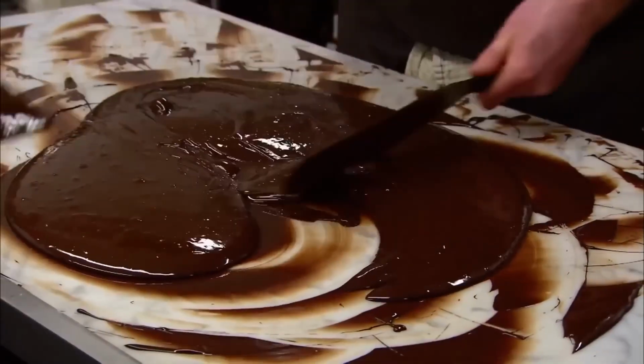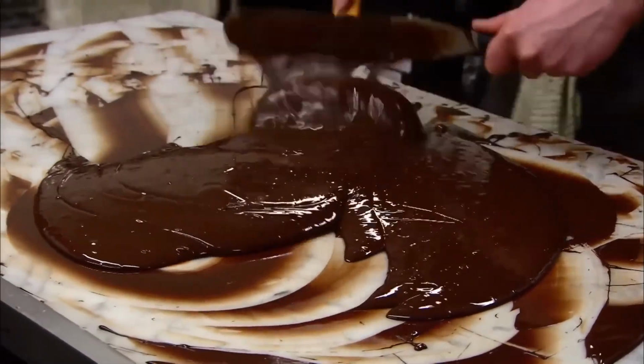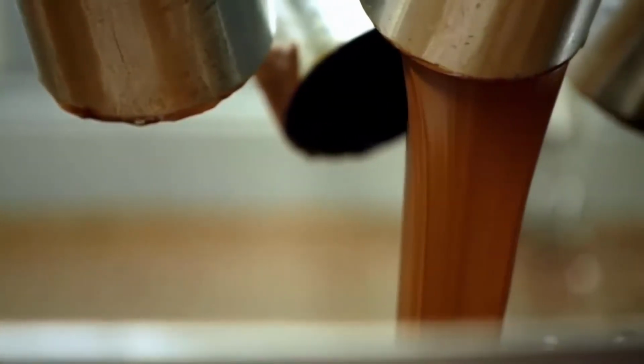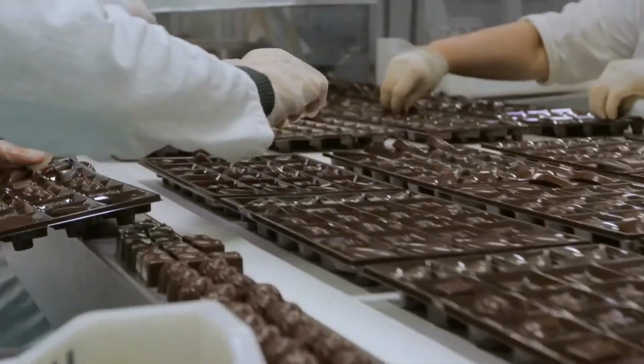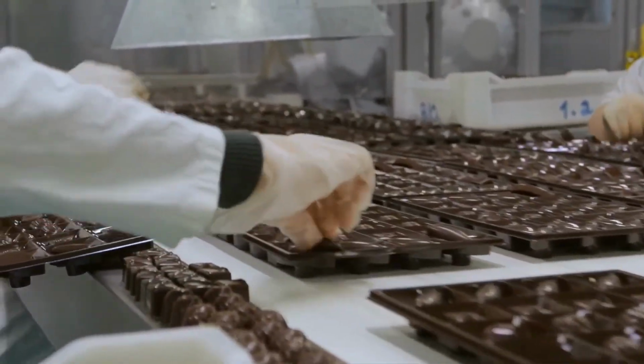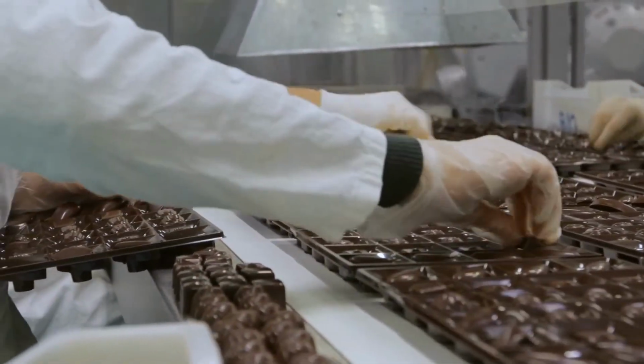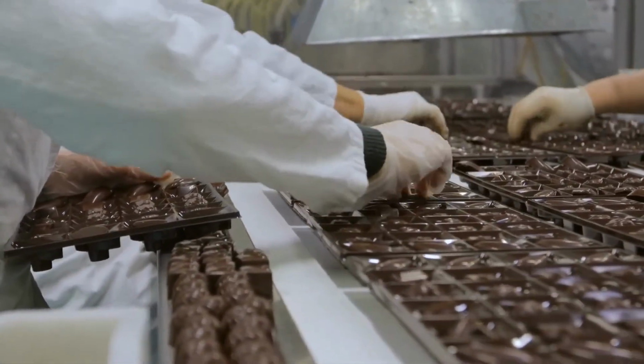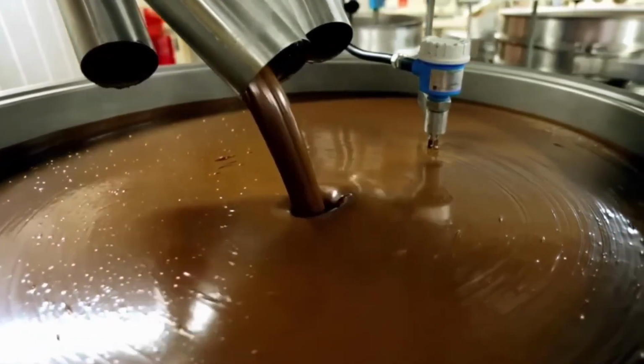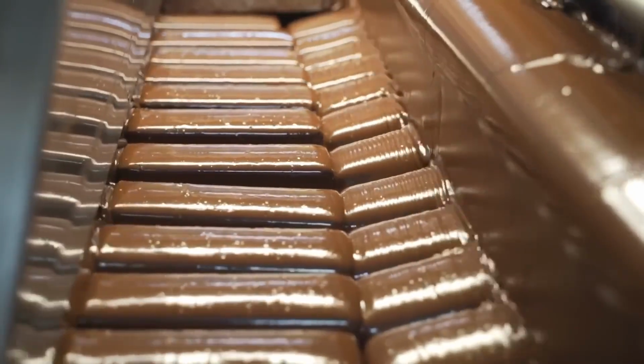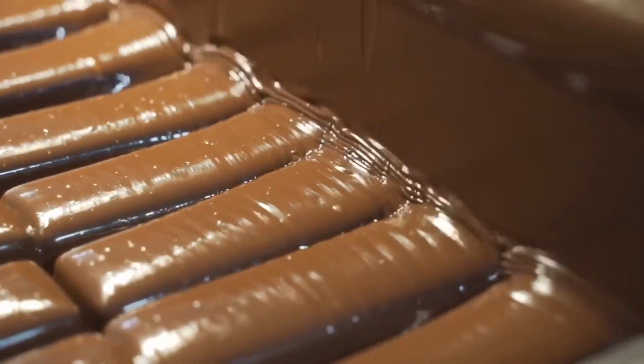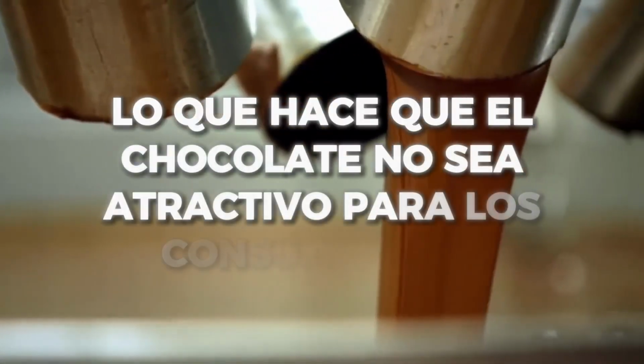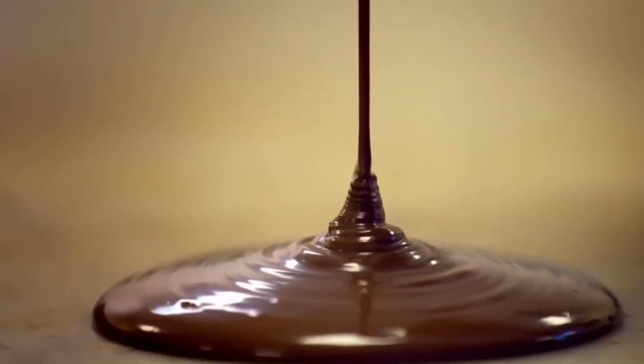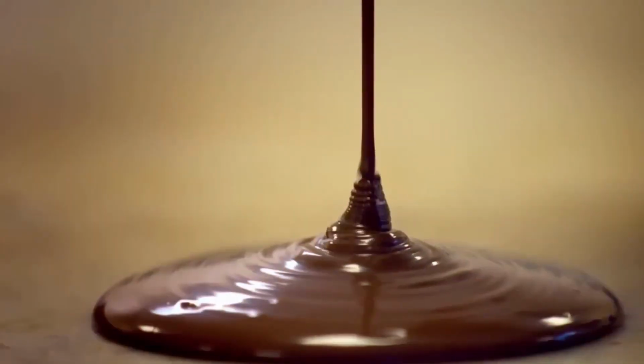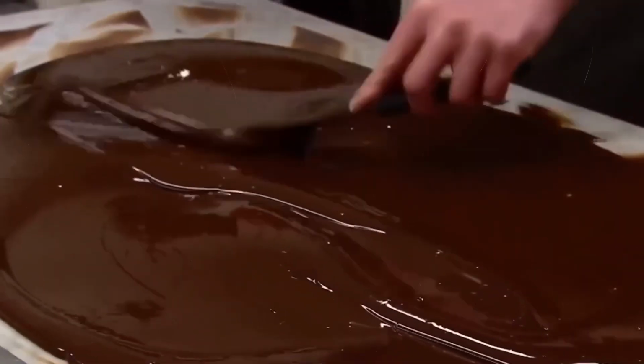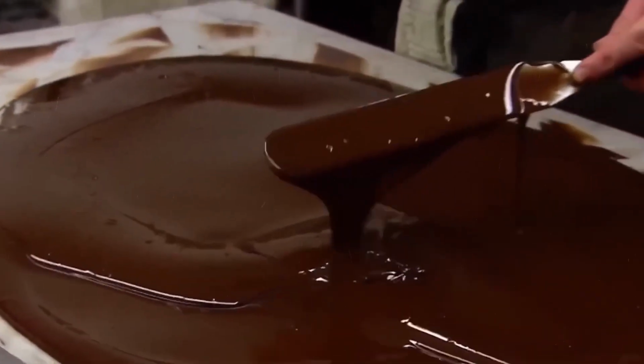Tempering is the step that determines whether the finished bar looks and behaves like a KitKat, or like a slab of dull, crumbling fat. Chocolate contains 6 crystalline forms of cacao butter, labeled Form 1 through Form 6. Only Form 5, called Beta 2, produces the glossy surface, the sharp snap, and the melting point of approximately 34 degrees C that allows the chocolate to melt cleanly on the tongue without feeling greasy.